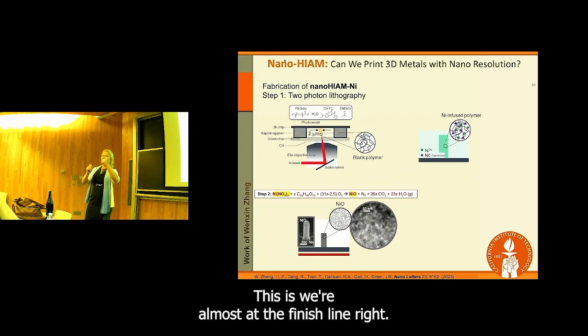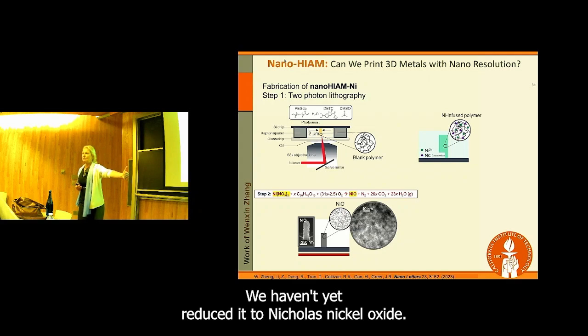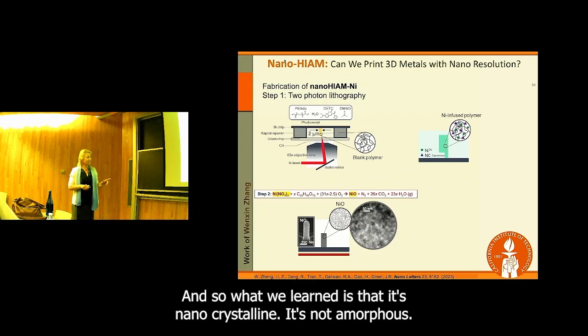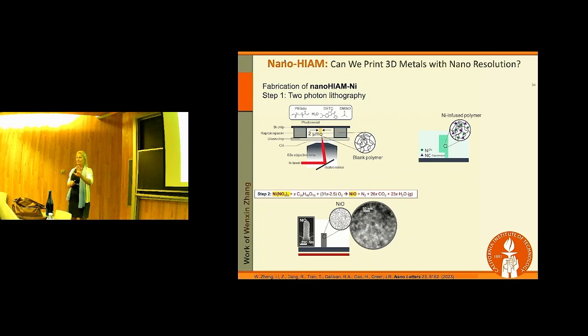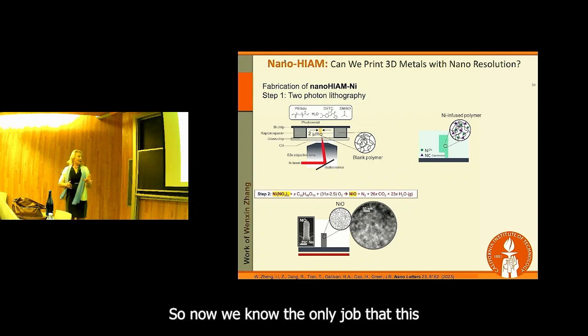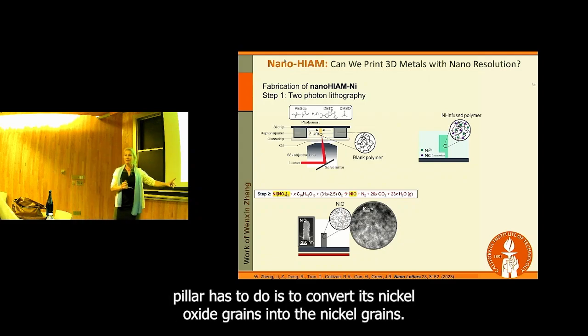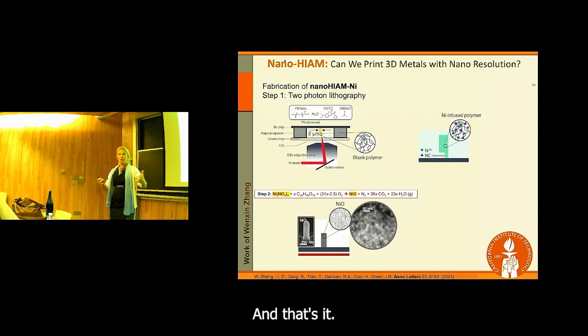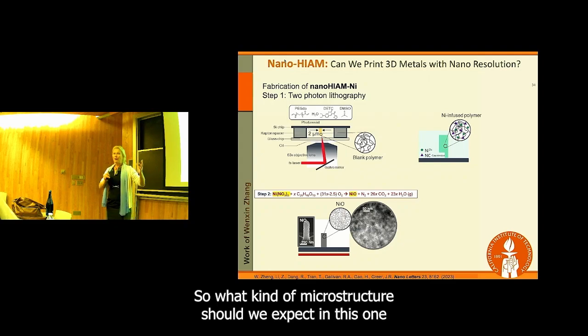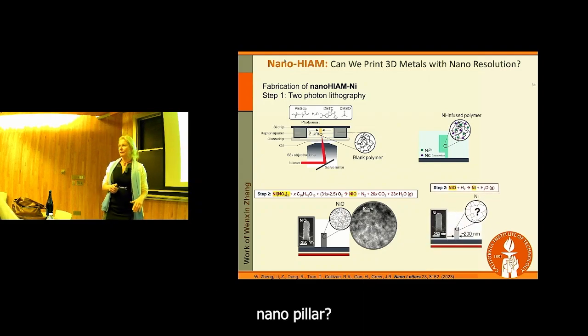We're almost at the finish line, right? We haven't yet reduced it to nickel. It's nickel oxide. And so what we learned is that it's nanocrystalline. It's not amorphous. This is important. So now we know the only job that this pillar has to do is to convert its nickel oxide grains into the nickel grains, and that's it. So what kind of microstructure should we expect in this one nanopillar?